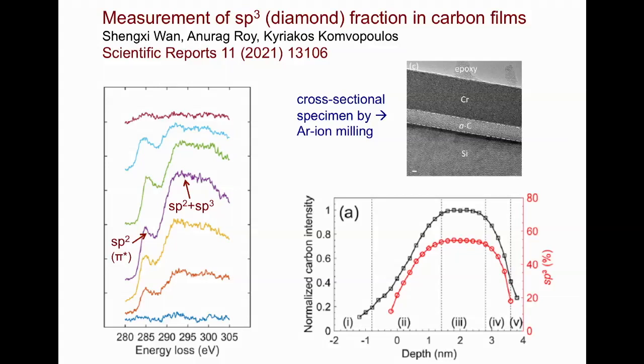These measurements required a cross-sectional specimen, which in this case was made by conventional thinning techniques, followed by argon ion milling, giving rise to the cross-sectional TEM image shown at the top right. Because this carbon layer is amorphous, the bonding type would not be easily measurable using electron diffraction.